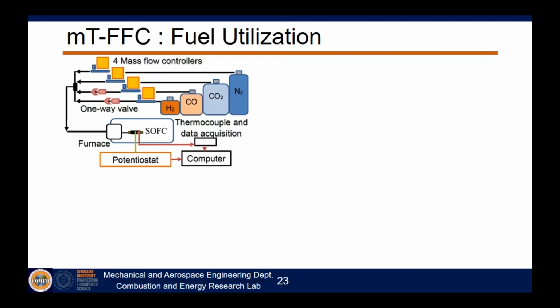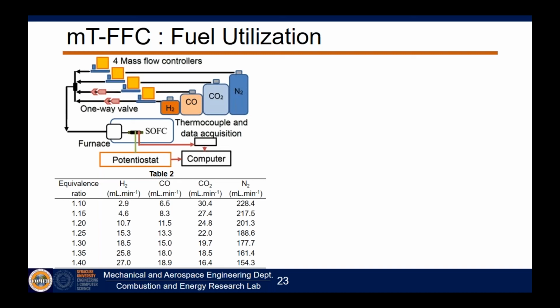So we pre-mixed the major gas species within the exhaust. We didn't use water. Water has some complications, and it's actually difficult to measure with a gas chromatograph. So this is ignoring water. This is basically the dry exhaust, but most of the composition of the exhaust is here. We then take this exhaust and we ultimately determine flow rates associated with it. Of course, at higher equivalence ratios, we have higher hydrogen, higher carbon monoxide that we're supplying, and in return, we have less carbon dioxide and less nitrogen that's being supplied.